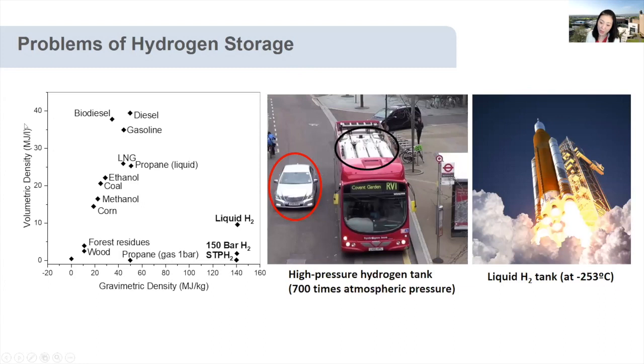So if you look at this energy density table, hydrogen is located in the bottom right. So if you look at the gravimetric density, energy per weight, hydrogen is twice or three times higher than diesel or petrol. If you look at the volume density, energy per volume, hydrogen is very low, nearly zero. Which means it requires massive volume of hydrogen to provide enough energy for a car to travel reasonable distance, for example.